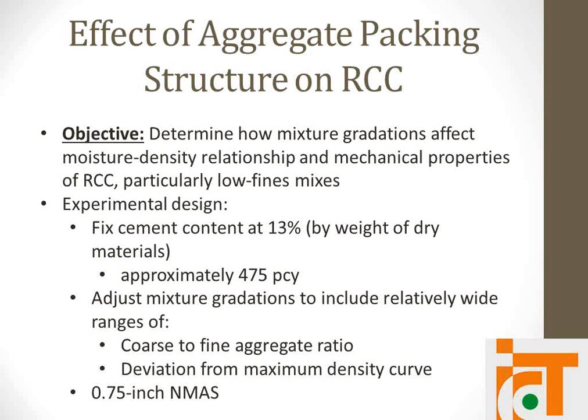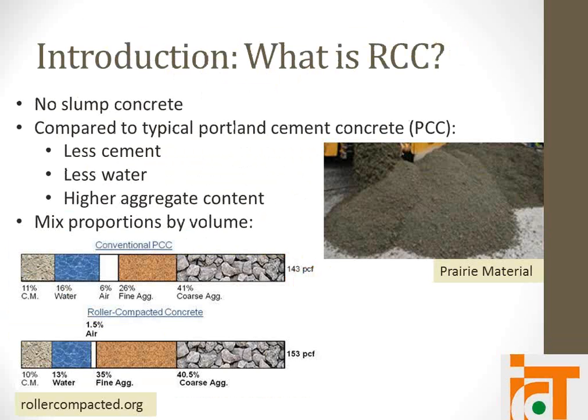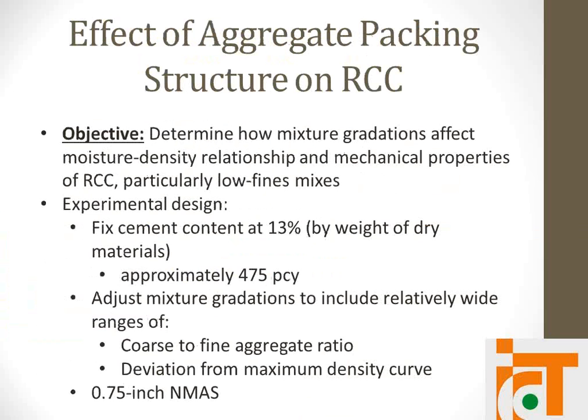So then for the gradations, kind of the two key factors that we want to look at were coarse to fine aggregate ratios. As we saw in that mixture, there's a lot higher aggregate content and specifically fine aggregates, so we wanted to take a look at the relationship between those. And also the deviation from the maximum density curve. Typically RCC is recommended to just make the gradation as close to the max density curve and you should be fine. And we set the nominal max size at 3/4 inch, which is recommended to get a good surface finish.